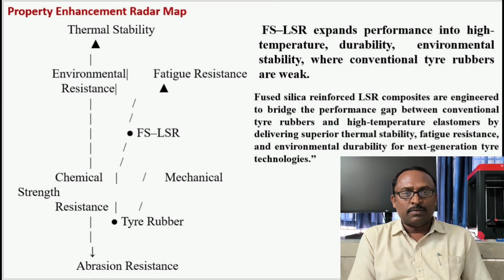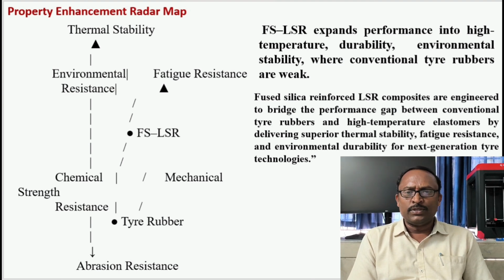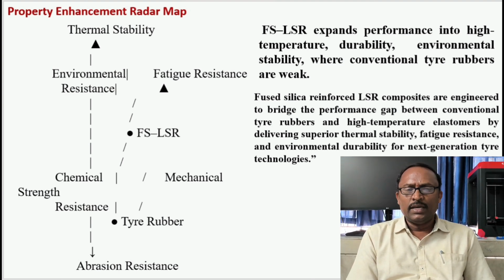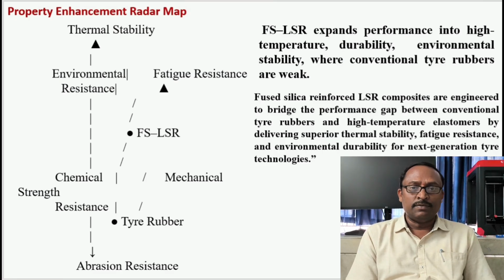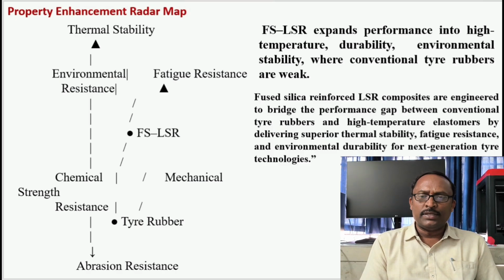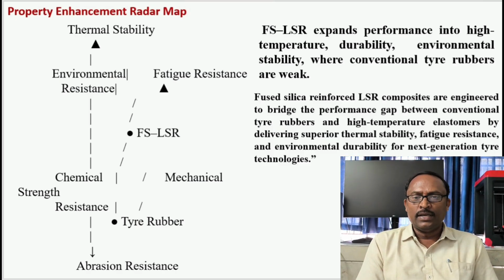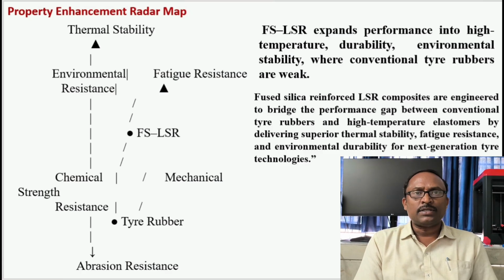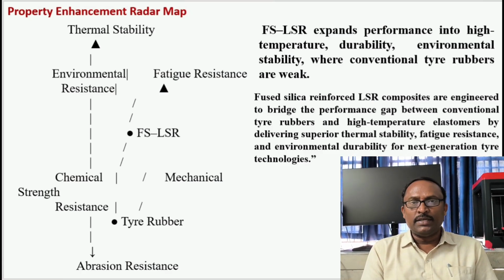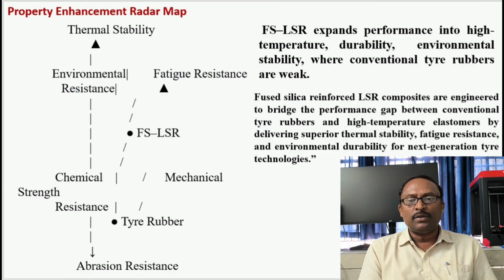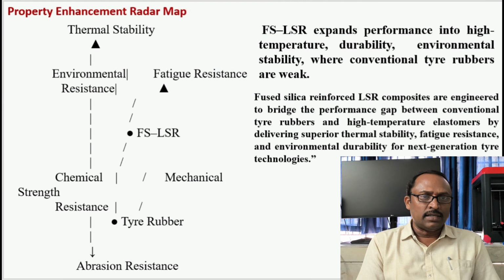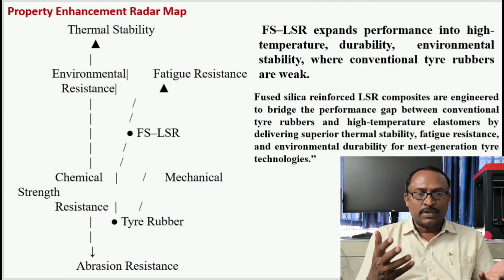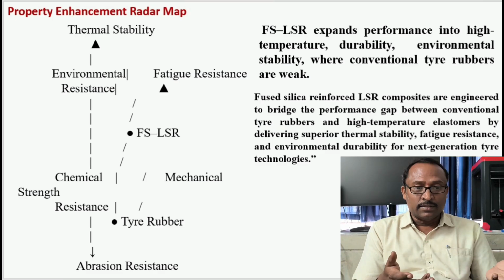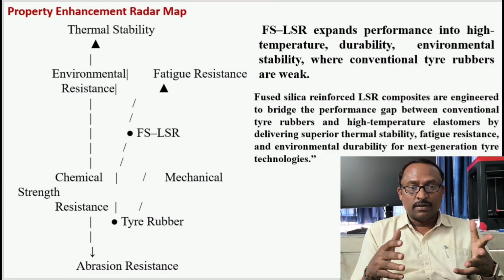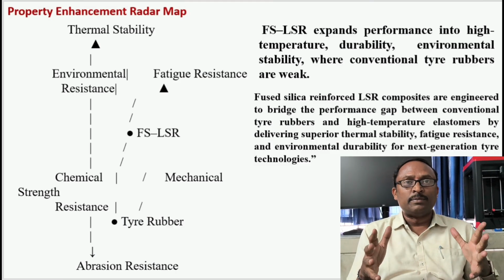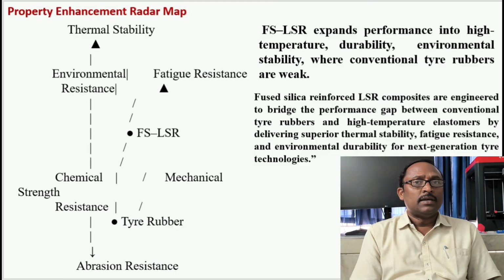Property enhancement radar map. Here the fused silica reinforcement expands performance into high temperature, durability, and environmental stability, where conventional tire rubbers are weak. Fused silica reinforced LSR composites are engineered to bridge the performance gap between conventional tire rubbers and high temperature elastomers by delivering superior thermal stability, fatigue resistance, and environmental durability for next generation tire technologies. The reason is thermal stability as well as abrasion resistance, chemical strength, mechanical strength, and also fatigue resistance. This is all accommodated in one material called fused silica reinforced liquid silicone rubber.